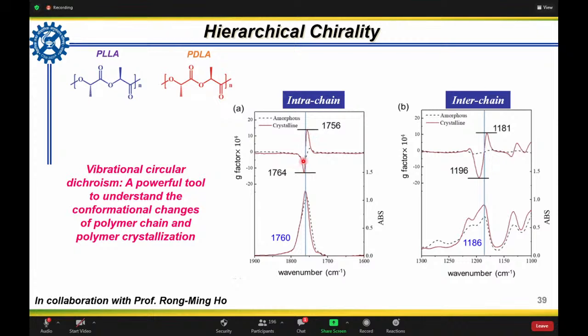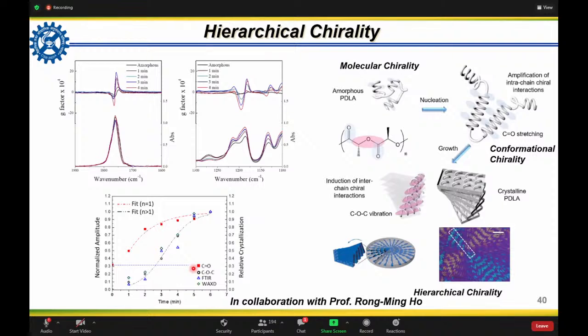And here, this talks only about the single chain. But when it comes to the interchain, when two polymer chains are coming closer, you can see the C=O interactions, and these peaks are coming up. The amplitude of these peaks has almost a direct correlation with the crystallinity. That's what we have shown. You can see here the VCD, X-ray and FTIR, and the degree of crystallinity we calculated at different times is exactly matching. And this will be the first report in the literature.